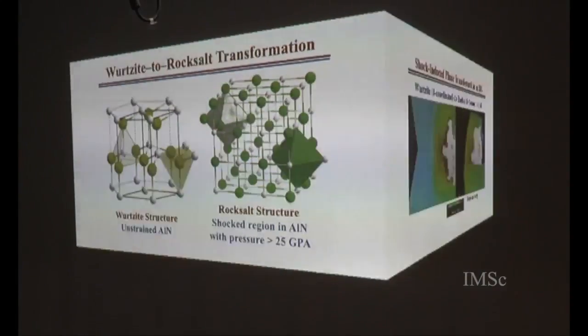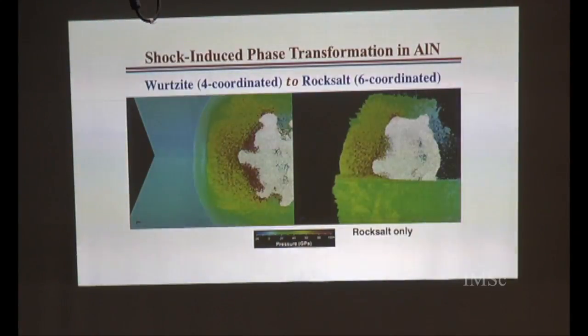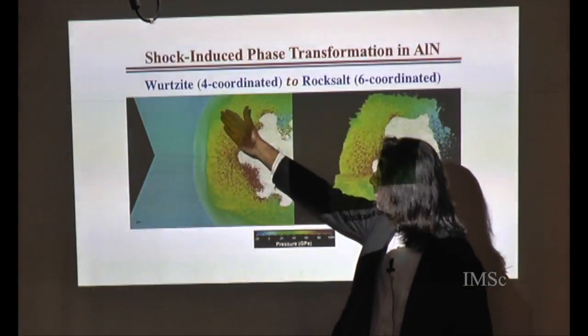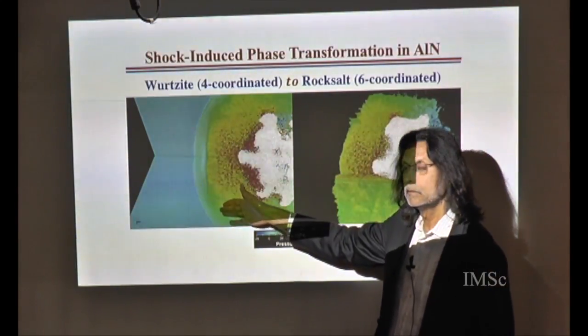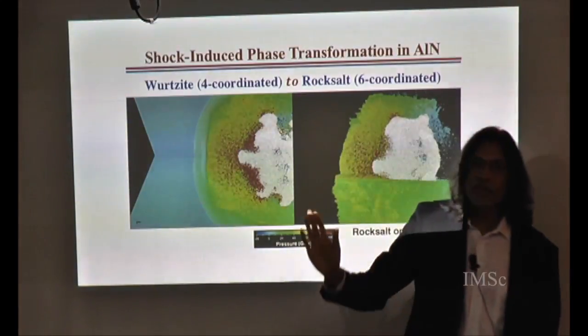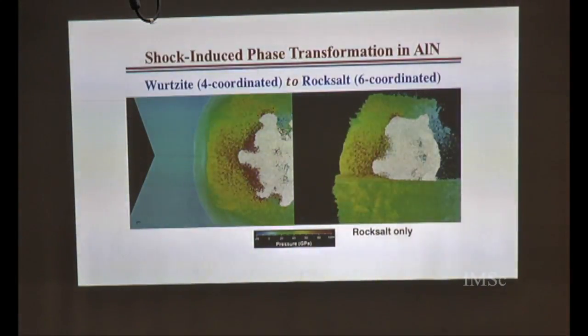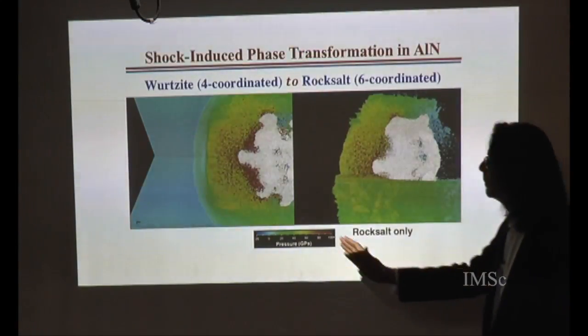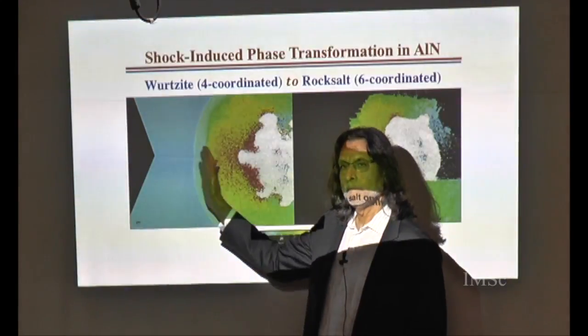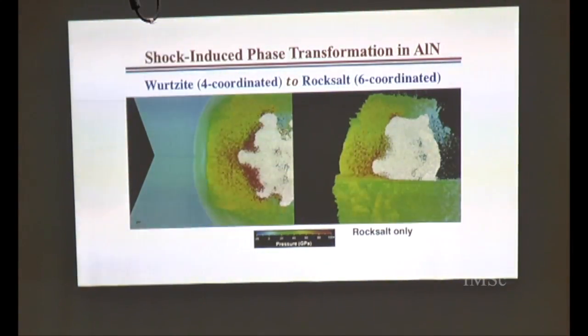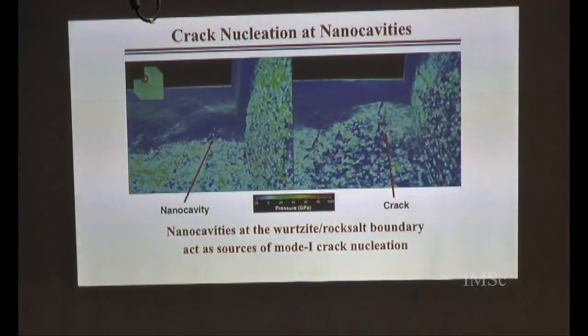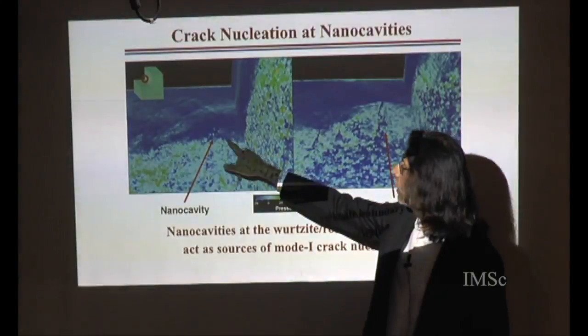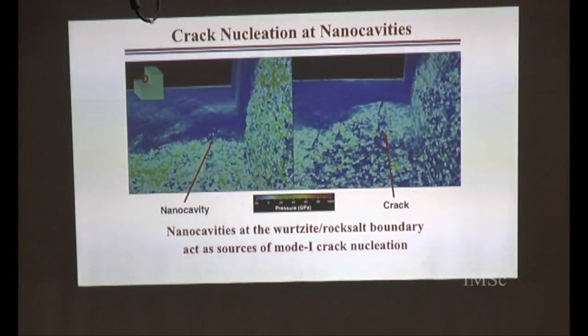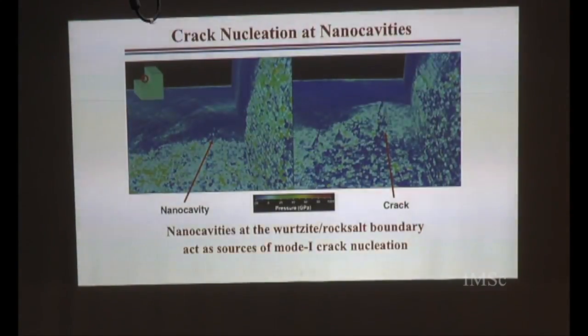What you're seeing over here, this part, is all rock salt. This part is Wurtzite, okay? So there's a structural transformation taking place in the system dynamically. And what happens next is the stress wave will go and be reflected from the boundaries. And when it is reflected, it comes to the boundary of the rock salt Wurtzite structure. At this interface, there is a lattice mismatch between the Wurtzite structure and the rock salt. And because of this lattice mismatch, there are strains at the boundary.